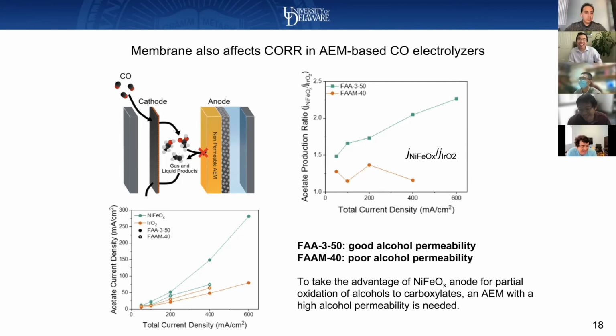Okay. Yeah. Every time I get that question, so thanks for asking that one. The answer is, it's hard. It's hard to know accurately what exactly the Faradaic efficiency for acetate is. But what we did is we run a system using iridium oxide and quantify the amount of ethanol. We assume that replacing the anode with nickel iron oxide doesn't change the amount of ethanol produced on the cathode. We use that to back calculate the acetate Faradaic efficiency. Of course, there's a lot of assumptions there, right? Because with the nickel iron, the cell potential actually shifts slightly, so there will be a little bit of difference there. It's just hard to know the exact number. We do our best. That's all I can say.